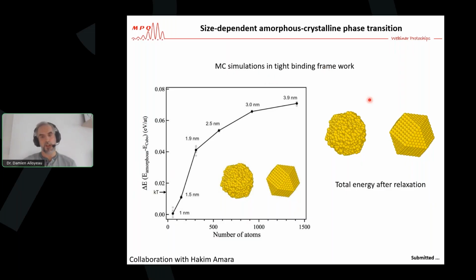tight binding framework. And Hakim has calculated the total energy of amorphous and crystalline nanostructures after relaxation for different sizes, different numbers of atoms and different sizes of nanostructure. And you realize that the total energy difference between those two structures goes below kT, so you have a biphasic regime when the nanoparticle goes below 1.5 nanometers.